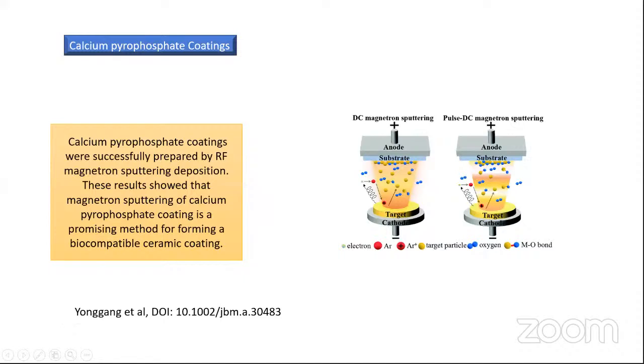Now, calcium pyrophosphate coatings. Calcium pyrophosphate coatings were successfully prepared by RF magnetron sputtering deposition. Thin films can be made by RF sputtering, and coating can be done on any particular substrate desired. These results showed that magnetron sputtering of calcium pyrophosphate coating is a promising method for forming a biocompatible ceramic coating. So any metal or material used in a human body that requires a friendly coating can be coated with calcium pyrophosphate using magnetron sputtering. So our body feels that it's a biomaterial, not a foreign material.